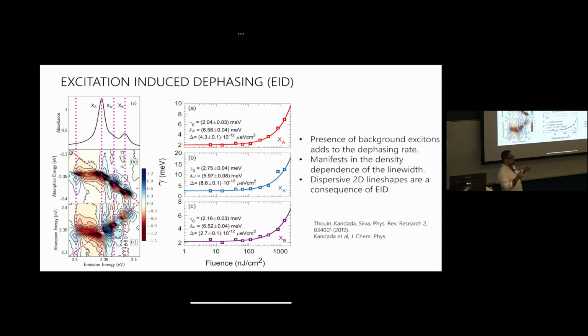But then there will be a part that will depend on density, exciton density. You crank up your laser power, you inject more excitons, and your density increases, and there will be a linear component, linear dependence on density. So it's a gamma zero plus, let's call it a delta times n, being the density. So you do that, and then you notice that your low density dephasing is measurably different between XA and XB. So already the fact that the excitons are dressed differently by the lattice means that they're protected in a different way to elastic scattering. Okay?